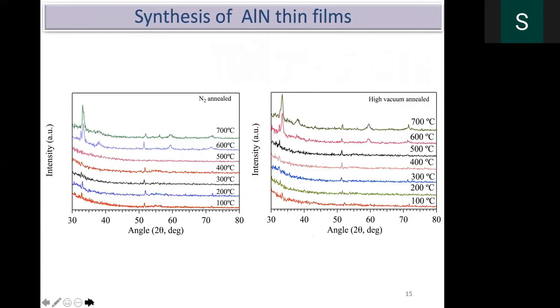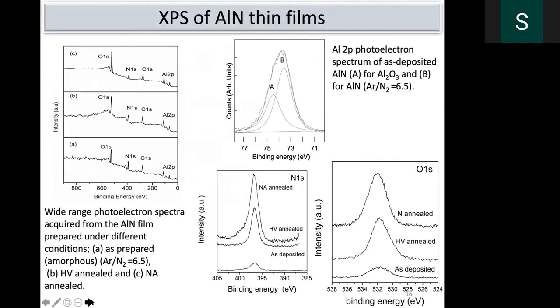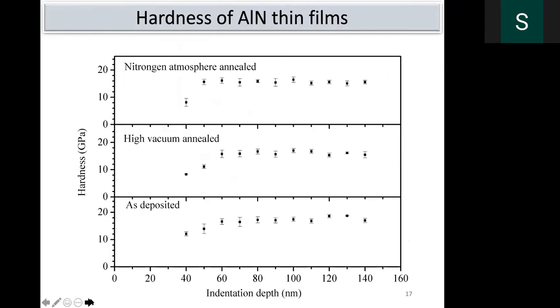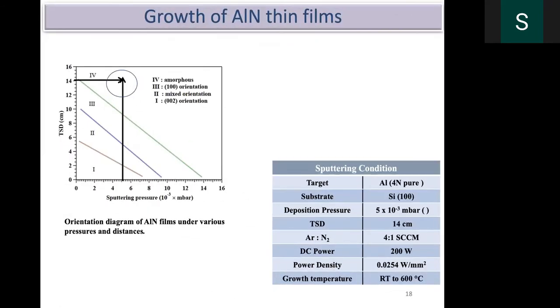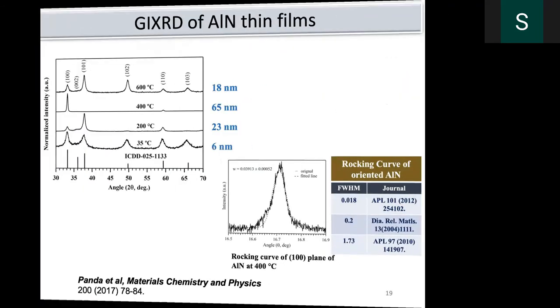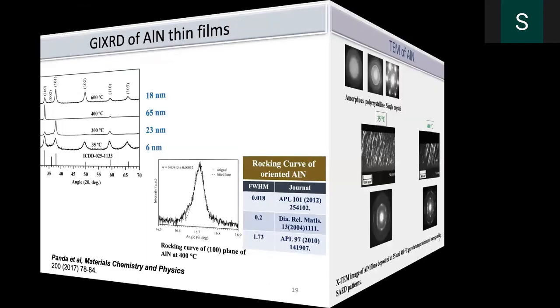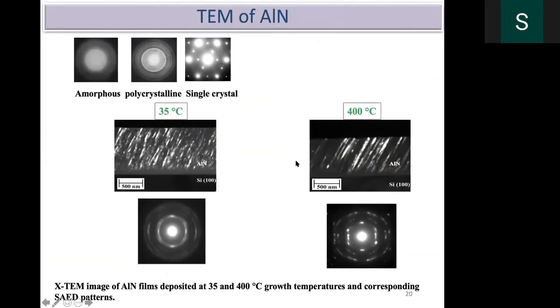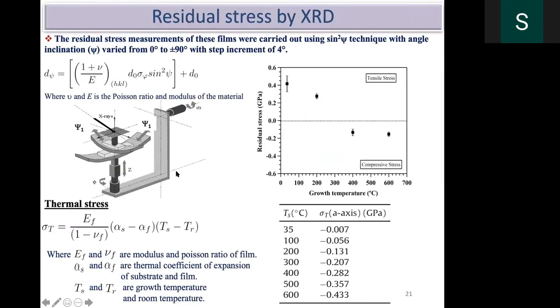That's what the TEM also shows, that the growth is not perpendicular. Rather, it is slanting. In all the cases, it's slanting. That is the main reason. And if you grow the films at different substrate temperatures, they will impart stress in the system.